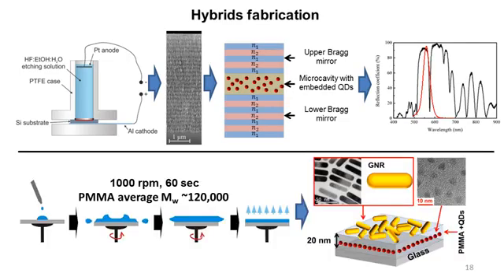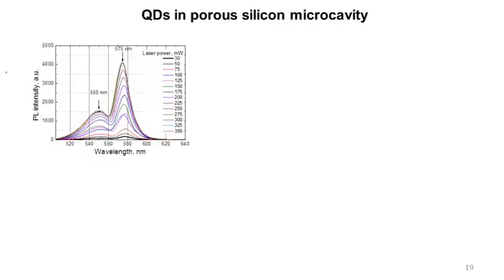To investigate the effect of gold nanorods on the two-photon absorption of quantum dots, we have fabricated two thin-film hybrid structures consisting of quantum dots in a 20 nanometers thick PMMA layer using the spin coating technique. We chose this thickness because it had been previously shown to be within the optimum range for the maximum photoluminescence enhancement. After fabrication of the initial 20 nanometers quantum dots in PMMA layers, one of two samples was covered with gold nanorods by dropping from aqueous solution and drying the samples, which resulted in the formation of the disordered surface films. At first we measured the photoluminescence properties of quantum dots in the porous silicon microcavity.